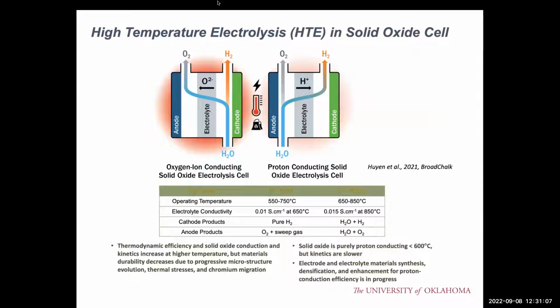So for the high temperature electrolysis, right now we have two kinds of them. One is oxygen ion conducting SOC, and another one is called hydrogen proton conducting SOC, because of the different electrolyte in the middle. On the left hand, as you can see, is the oxygen ion conducting electrolyte. So the water is fed at the right hand side, and after the splitting, the oxygen ion transports through the membrane. And in the other case, the proton is transporting through the membrane. So what's the difference? You want to say why? So the table lists the difference between these two different kinds of SOC.